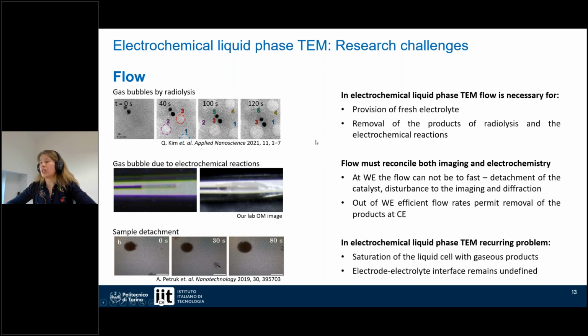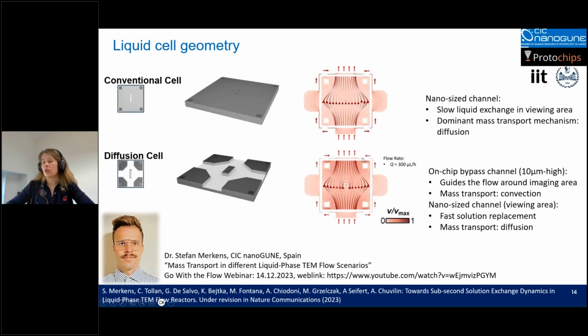In liquid phase TEM, the flow must reconcile both imaging and electrochemistry. We would wish that the flow at the working electrode is not too fast, so as not to detach the catalyst and not to disturb the imaging and the diffraction, but away from the working electrode, efficient flow rates permit removal of the products at the counter electrode, which is also very important. So efficient flow is very important, and the efficiency of the flow will depend on the liquid cell geometry. And in the previous Go with the Flow webinar in December, Dr. Stefan Merkens from Spain was speaking about the mass transport in different liquid phase TEM flow scenarios.